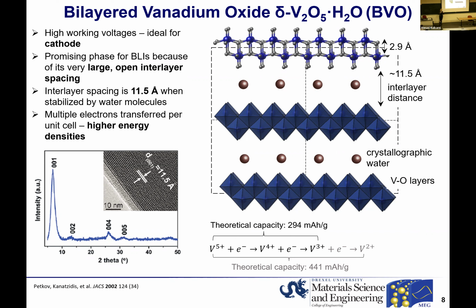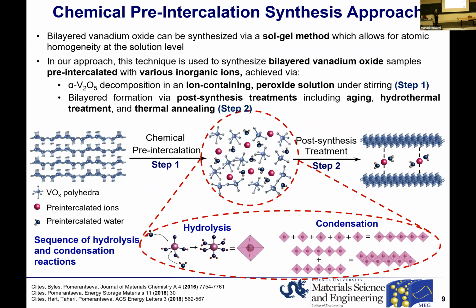So we wanted to develop a method in which we would synthesize exactly the same material, but with lithium ions being already incorporated into this interlayer region. And thanks to the very rich work done by Jacques Livage on sol-gel processes for the synthesis of transition metal oxides, I knew that with certain precursors, the transition metal oxides could be dissolved to form a solution using hydrogen peroxide in an aqueous environment.